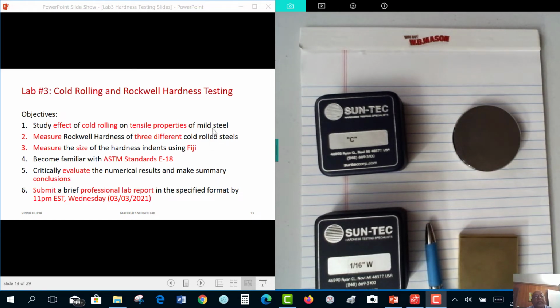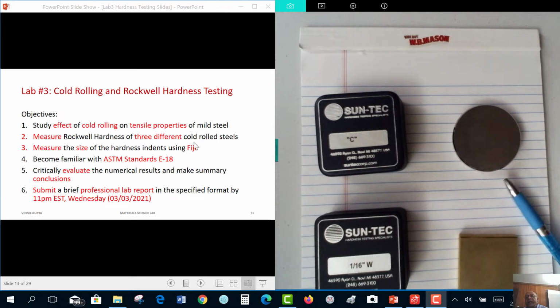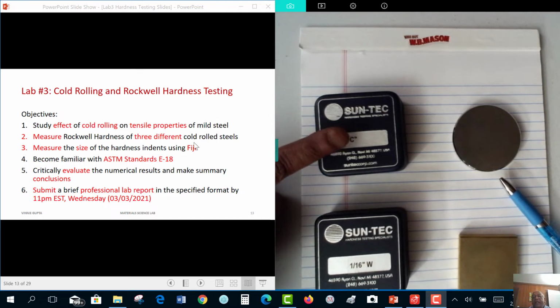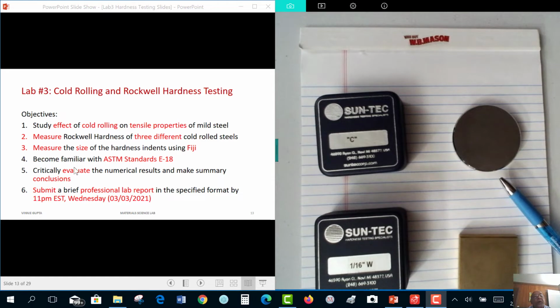We are going to focus in my demo on 3 different cold rolled steels. So I have 3 different steel samples which have different hardnesses. I'm going to make a Rockwell C indentation on them. And then we are going to measure the size of these indents using Fiji. We are going to talk about different ideas in hardness. And I hope you have downloaded this ASTM standard E18, and I hope you become really very familiar with it. And then, as usual, you are going to critically evaluate numerical results and make summary conclusions on your specimen.